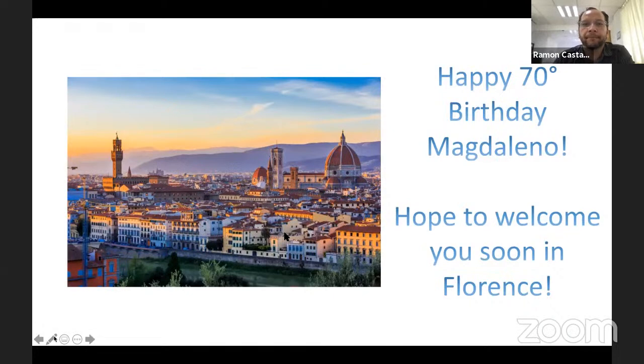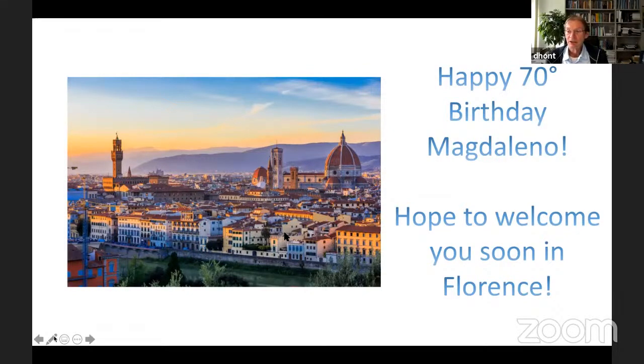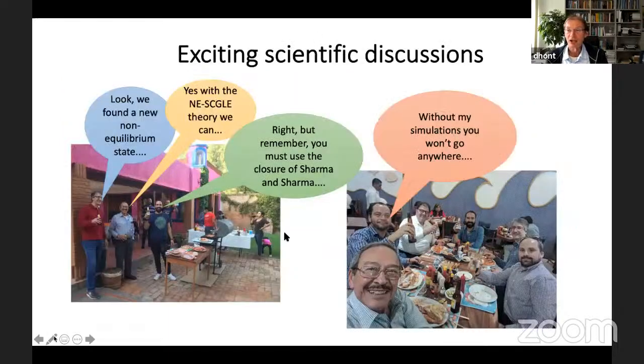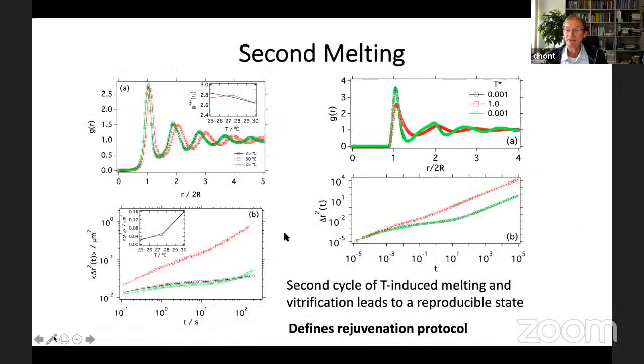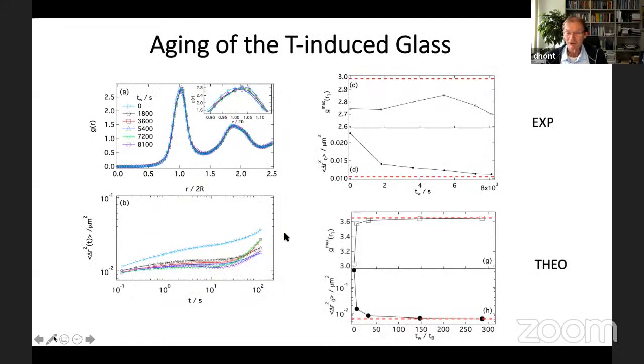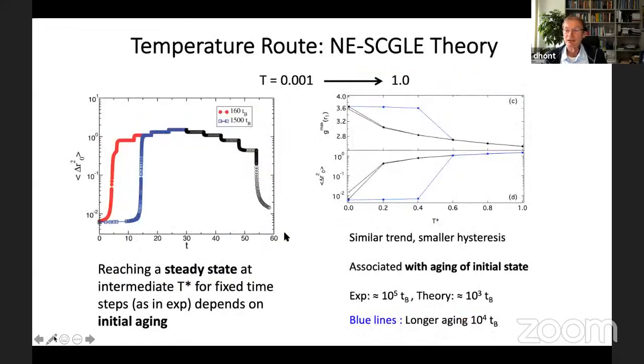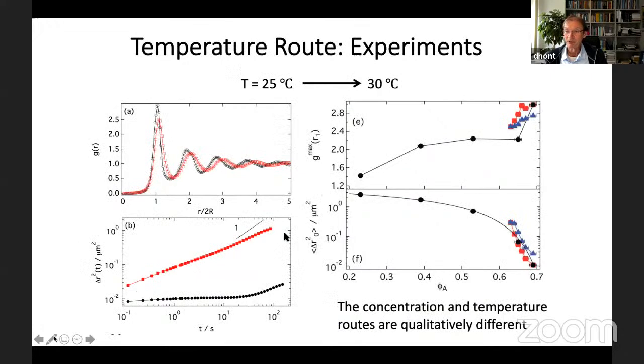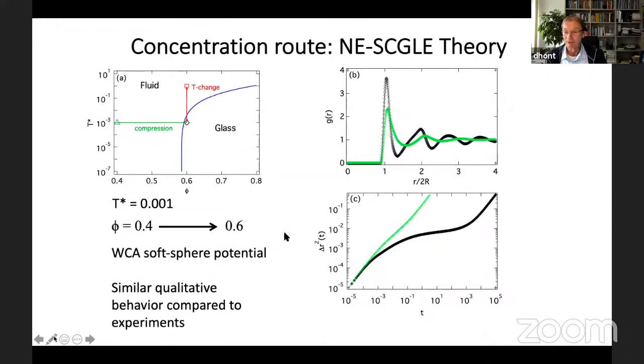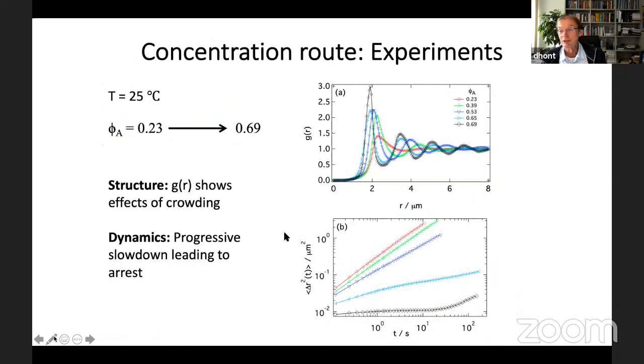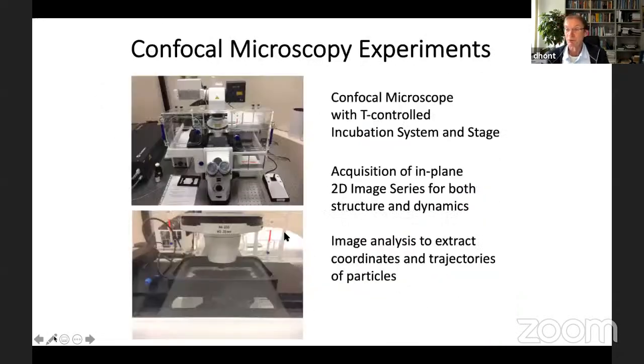So I have a little bit of a difficulty understanding how you can have a single glass if the size ratio is larger than about 1/9. If the size ratio is less than 1/9, the small spheres will be able to move through the holes in between the big ones. So you can have a single glass where the big ones are fixed in space, so to speak, and the small ones can diffuse through the holes that are left in between the big ones.